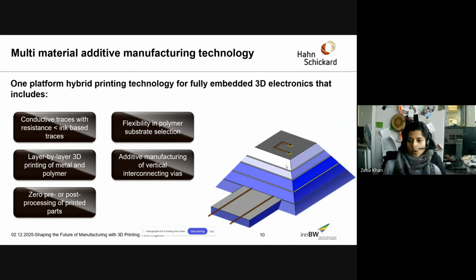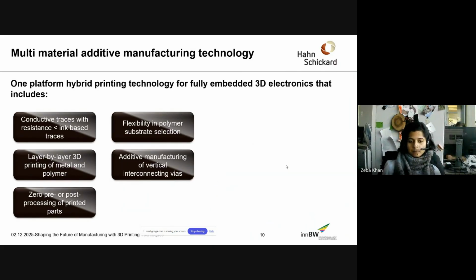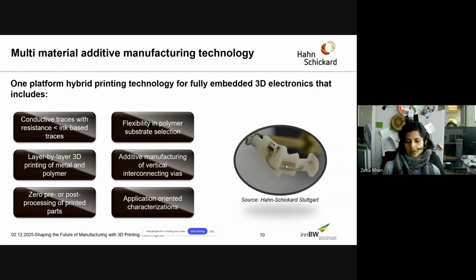And overall, this process does not require any pre or post processing. As I mentioned previously, the substrates for most of the dielectric based inks need some kind of surface treatment to ensure that the inks are able to adhere to the surface substrate. And this is something we are able to eliminate with the help of our polymer portfolios. And we also do not need any post-processing of the printed parts. That means we do not need any sintering since our metal is in the bulk form. And finally, we have application-oriented characterizations that we have developed here. That means we have done reliability tests, we have done some industrial scale thermal shock tests, etc.